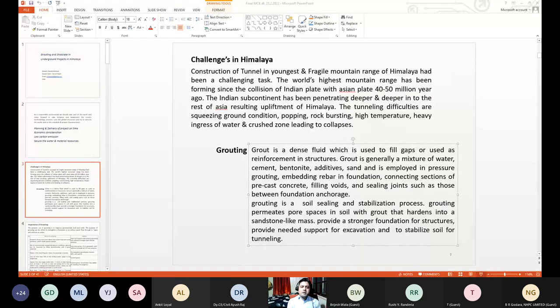What is the most frequent reason for grouting in tunnel? Pre-excavation grouting by cement, microfine, ultrafine and colloidal silica can be done. Loss of more than 50% of drilling water approximately in any single hole: cement grout can be done. Ingress from any single probe hole of 3 liters per minute, or total ingress of 15 liters per minute or 30 liters per minute per 100 meters in the underground excavated portion. Inflow can be measured by installing an automatic V-notch at 90 degrees. Cement grout can be done.